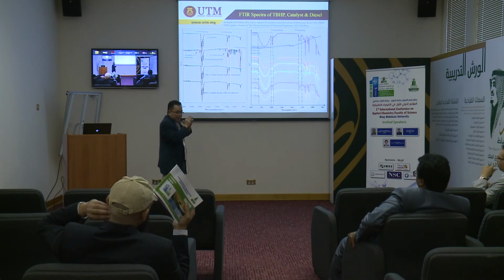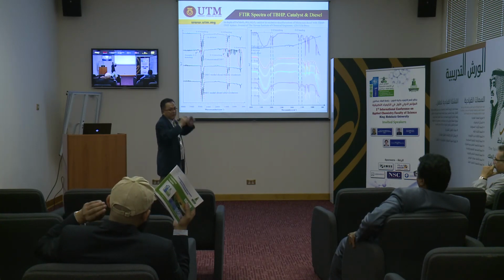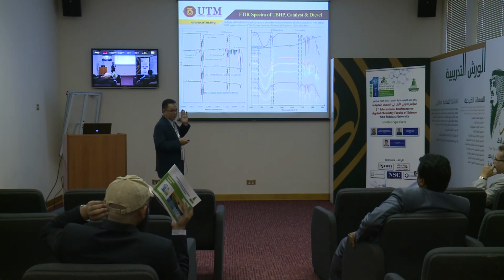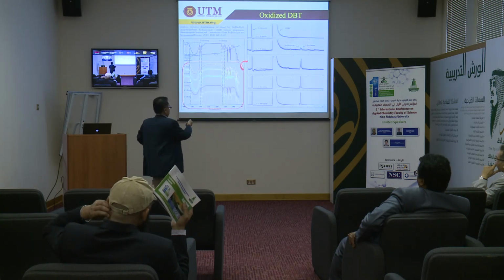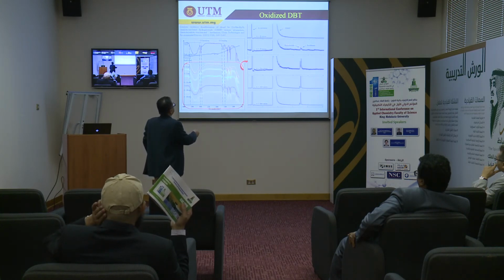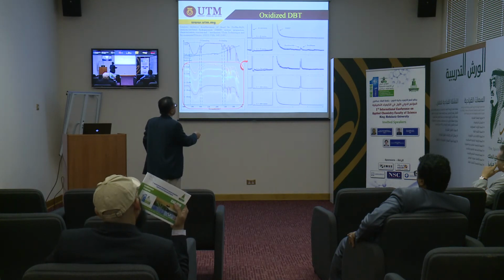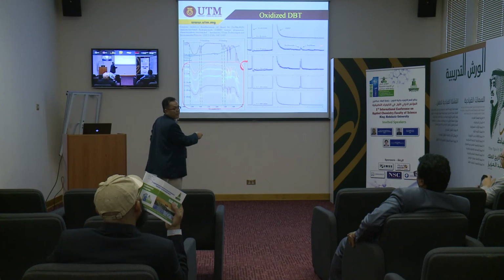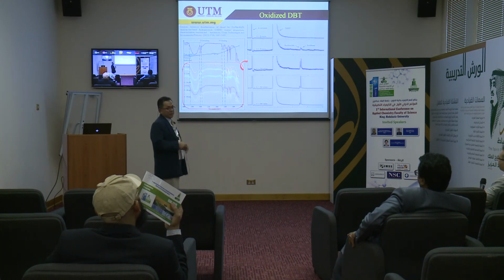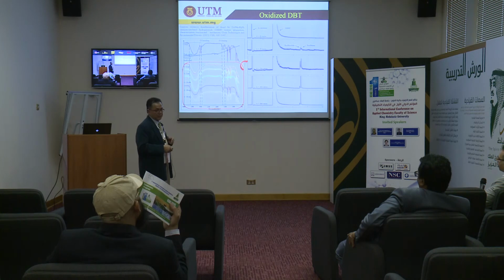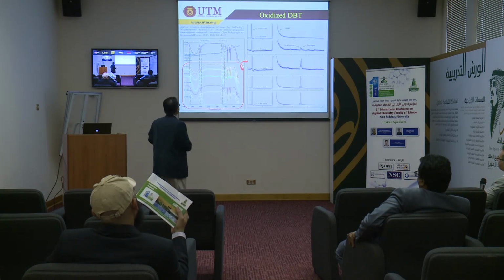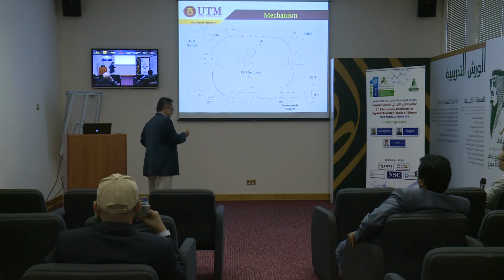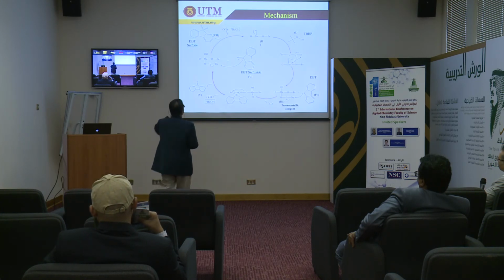Then after that, it dissociates to form the active species, and then reacts with the sulfur compound to form sulfur oxide or sulfone. We monitor it using a GC, whereby at first they form sulfur oxide plus sulfone, but later on, as time increases, we can see that sulfone is the major product. Then we remove it using solvent extraction with DMF. So, by all the data we obtained, we propose the mechanism.